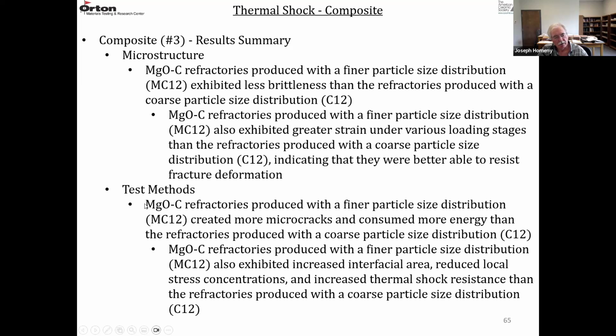And then for the test methods, the refractories produced with the finer particle size distribution created more microcracks in the matrix and at the matrix particle interfaces, and it consumed more energy than the refractories produced with the coarse particle size distribution. So these composites that were made with the finer particle size distribution have also increased interfacial area because of the finer MgO particles that tended to reduce the stress concentrations, increase thermal shock resistance, and that was relative to the coarse particle size materials.